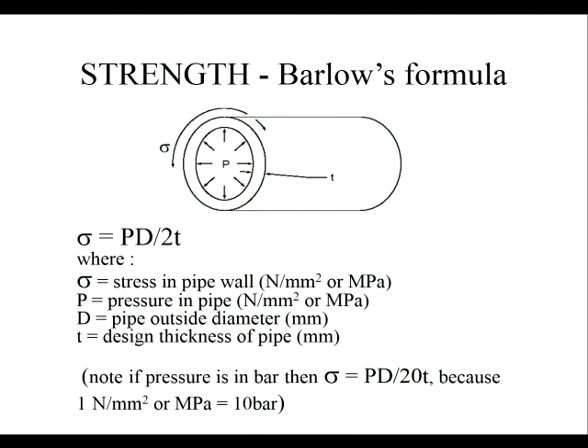There are very many proofs in mechanical engineering textbooks about this, but that's a very standard result. Now sometimes you'll see PD equals 20T, and that's just because the units are different. The equation is exactly the same, but if we put the stress in bar, 1 megapascal equals 10 bar, so you get a factor of 10 appearing in the equation from the two. So you notice here I've put the units, and the units